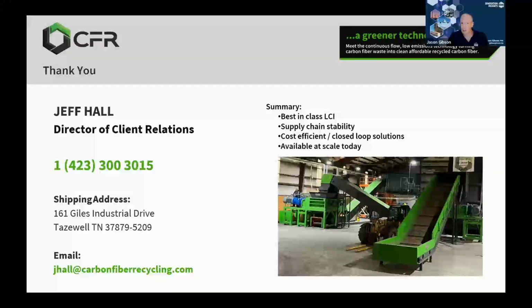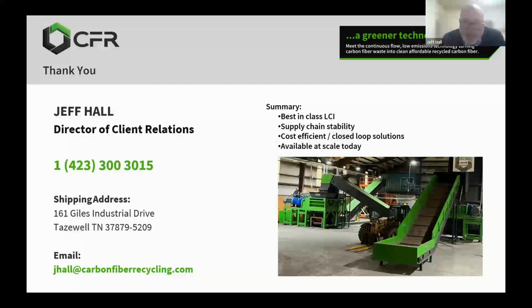Great. Next question. What are the fiber lengths in the agglomerated recycled fiber? So we refer to that material as our 15 millimeter. As you can probably see from the picture, it's a variation. So if you look at the bell curve right now, that material lands nominally around 15 millimeters. Because we are doing some upgrades, it'll change the amount of fines available in it. So we don't have a fiber dispersion chart to provide, but it is something we'll be developing pretty shortly. Nominally, I would say it's about 15 millimeters.